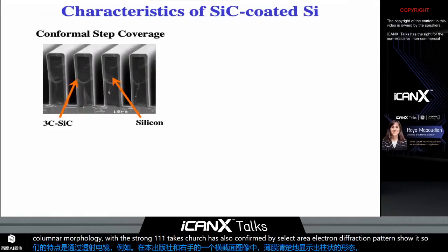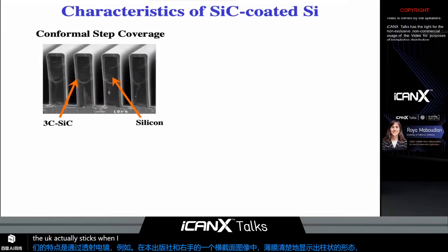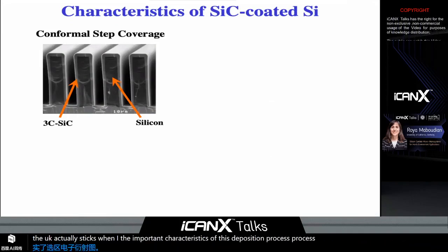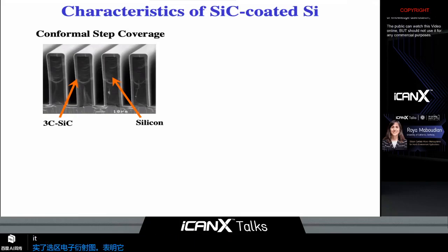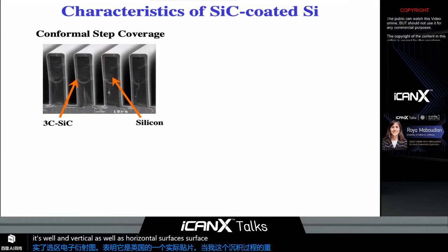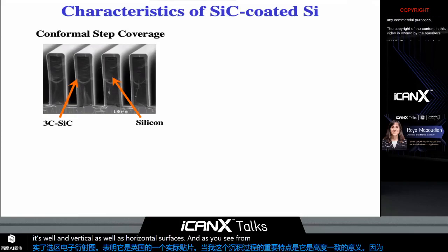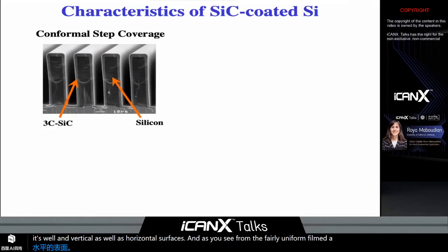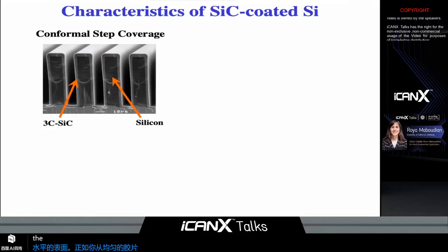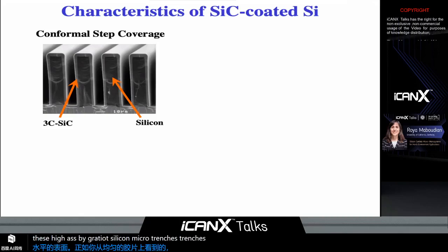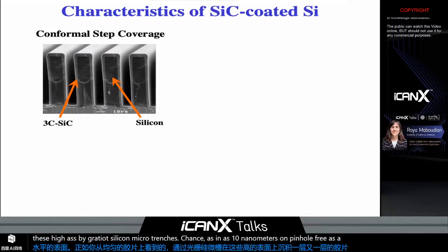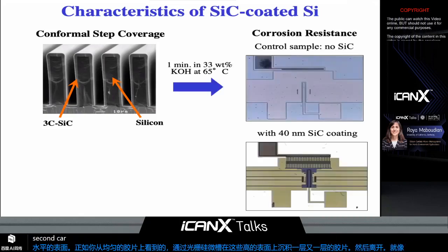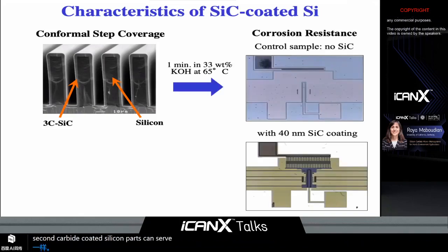One of the important characteristics of this deposition process is that it is highly conformal, meaning it deposits well on vertical as well as horizontal surfaces. As you see from the fairly uniform film, silicon carbide film deposited on these high aspect ratio silicon microtrenches. Films as thin as 10 nanometer are pinhole free, as evidenced by the fact that the silicon carbide coated silicon parts can survive a very aggressive silicon etchant, namely hot KOH.